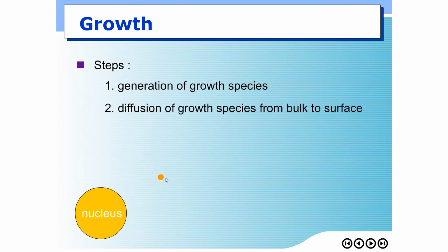This growth species, as I said, has the ability to move just like an atom. Movement of growth species can be done by diffusion. Okay? So, the concentration of growth species around here is supposed to be higher than the concentration of growth species on the surface of the nuclei. Why did I say that? Because whenever we have growth species on the surface of nuclei, growth species would become part of the solid, and the concentration of growth species in liquid around that area would become 0.